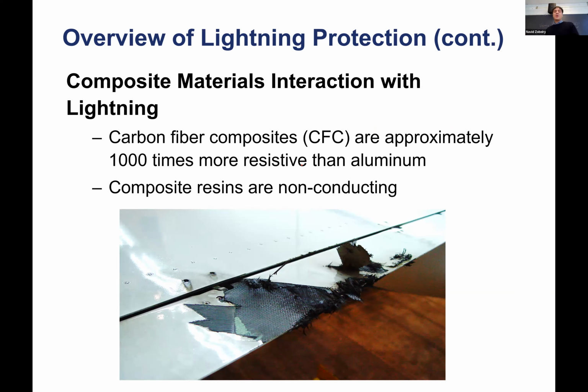It's a composite which was unprotected, let's say. So the lightning strike comes in, energy builds up locally, and in this case it's carbon fiber, so it's going to dissipate the energy a bit, but it's going to damage the part. If it was glass fiber, it would be a very different story. It will just puncture through it.